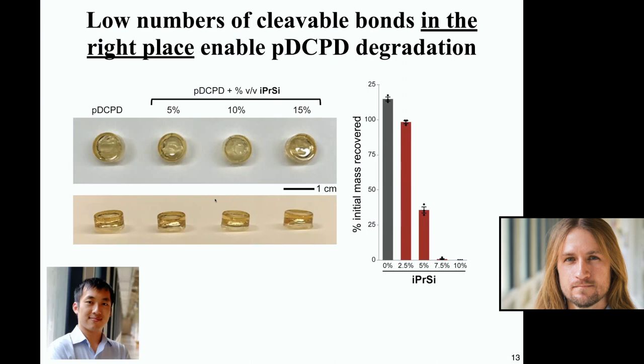What we find quite strikingly is that this sample of pDCPD without any of our molecule in it doesn't degrade at all, as quantified here by the percentage of initial mass recovered. So we actually recover back after exposure to fluoride all of the material, if not even more, because it swells somewhat in the fluoride solution. When we add 2.5% of our molecule, it still doesn't degrade. At 5%, it degrades significantly, but quite strikingly, once we get to 7.5% or 10%, we completely dissolve away this material.